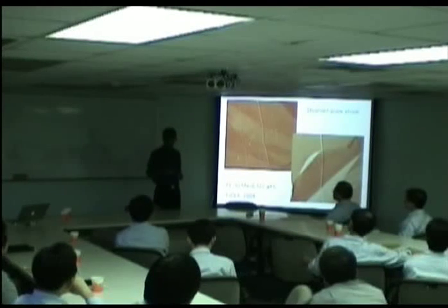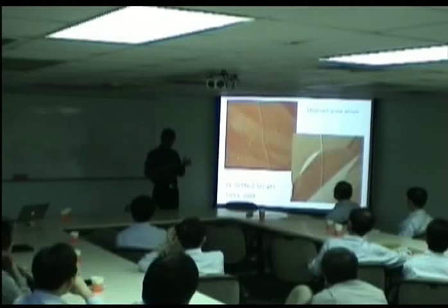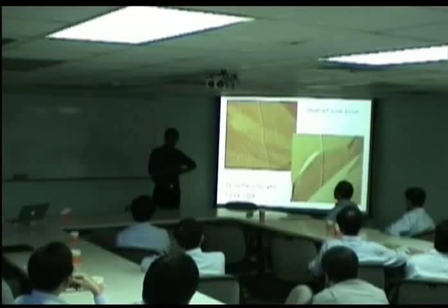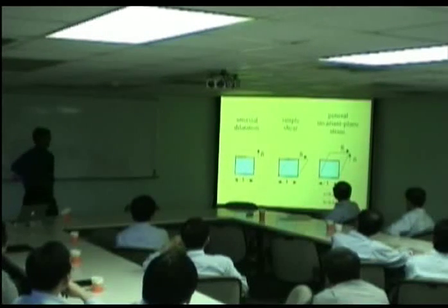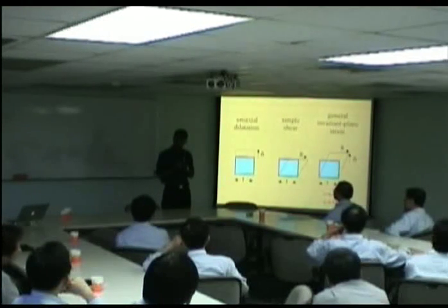And of course, in the last lecture I showed you an atomic force microscope image of the shape change due to bainite. In TRIP-assisted steels, the austenite is transforming to martensite. And the martensite itself will produce a shape change, and you can see these scratches have been deflected by the martensitic transformation. It's well known that you can measure the shape deformation by looking at scratches. So it's a physical displacement. And the way in which this displacement occurs is unique.